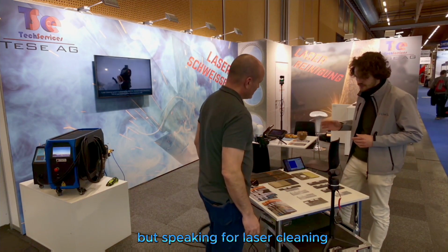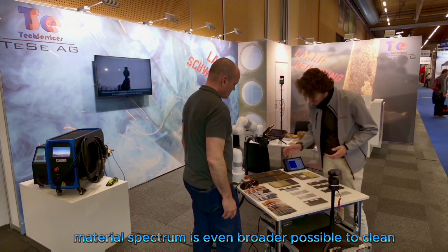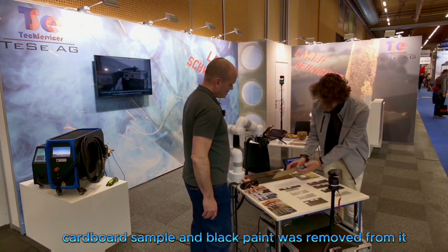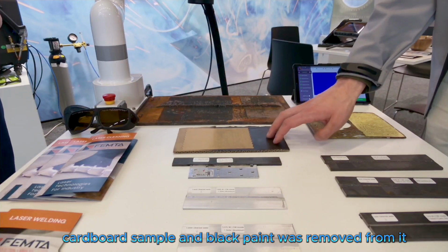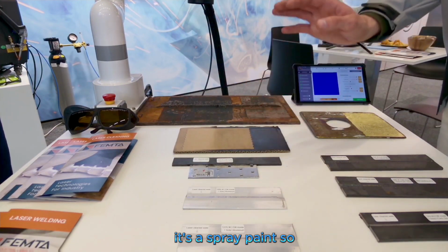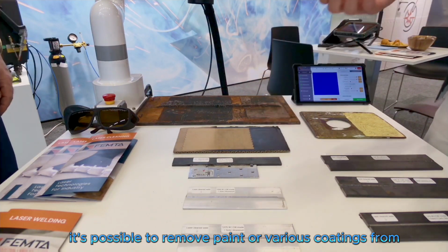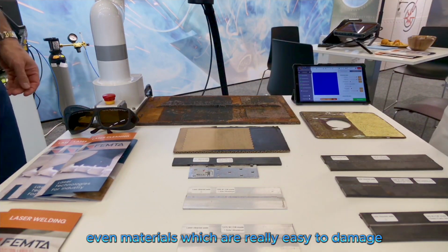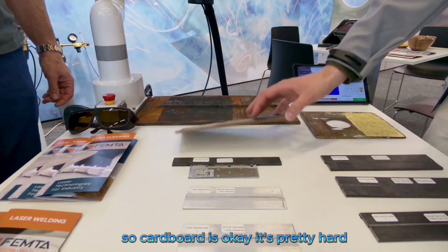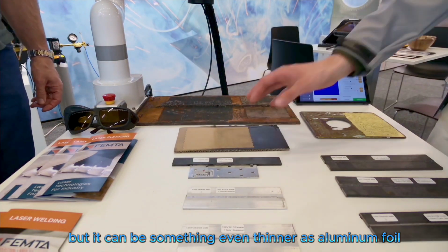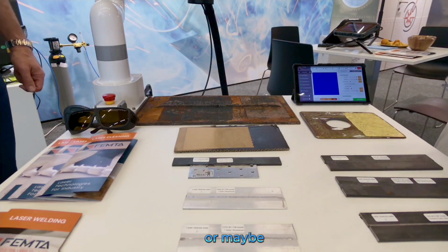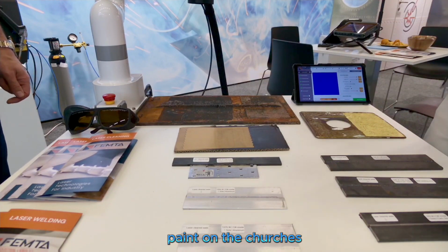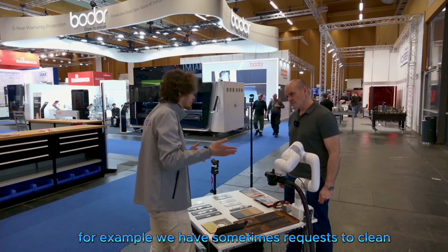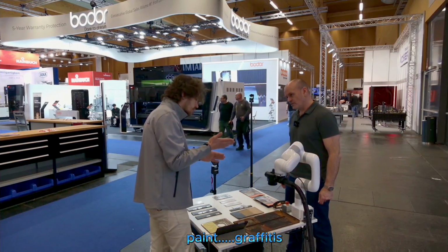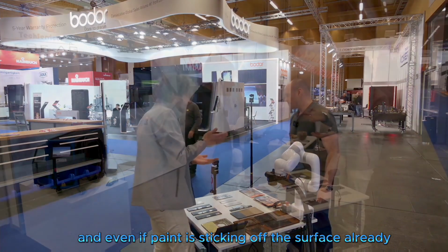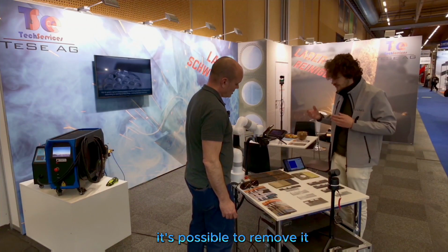But speaking of laser cleaning, the material spectrum is even broader. We have here a paper, cardboard sample, and black paint was removed from it. It's a spray paint. So it's possible to remove paint or various coatings from even materials which are really easy to damage. So cardboard is okay, it's pretty hard, but it can be something even thinner like aluminum foil, or maybe paint. On churches, for example, we sometimes have requests to clean paint graffiti, and even if paint is sticking off the surface already, it's possible to remove it without damaging it.